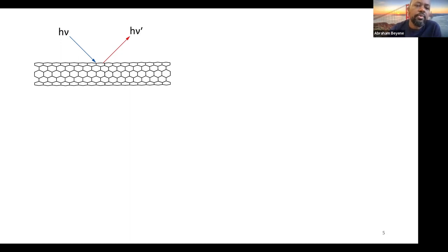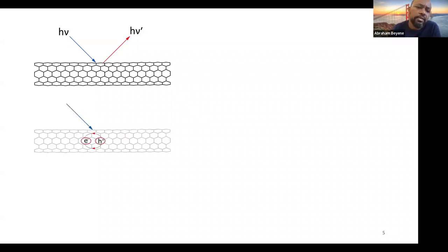And in this representation, in this cartoon, this is precisely how you describe fluorescence from just about any kind of fluorophore. However, when you take a closer look at this system, there are some really intriguing differences that are very important to understand why we can even make sensors out of these systems. And the reason is because the so-called excited state of this molecule is actually an electron hole pair or exciton that gets generated on the surface when a photon gets absorbed, right? And the best way you can understand these electron hole pairs is just regions of this relative positive and negative charge that are coupled electrostatically through Coulombic interactions and remain on the surface of these nanomaterials.